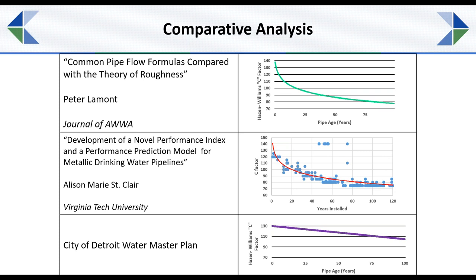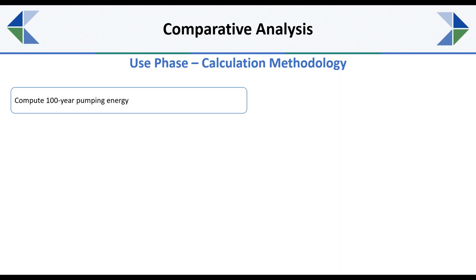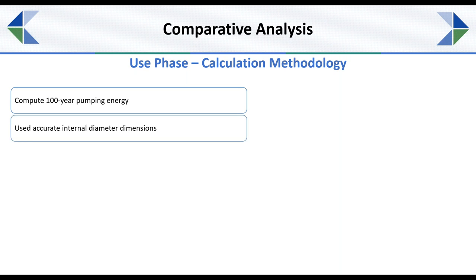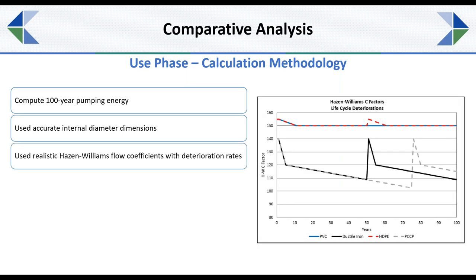So we ended up utilizing a degradation factor like what you see on the bottom row there, where it's a linear decrease over time. So for actually calculating the pumping energy required, we computed for that given 100-year life cycle. And so we use the accurate internal diameter dimensions, or internal size dimensions. We use the Hazen-Williams flow coefficients that I showed previously with the appropriate deterioration rates. And so doing so ends up getting the graph like what you see here on the right.